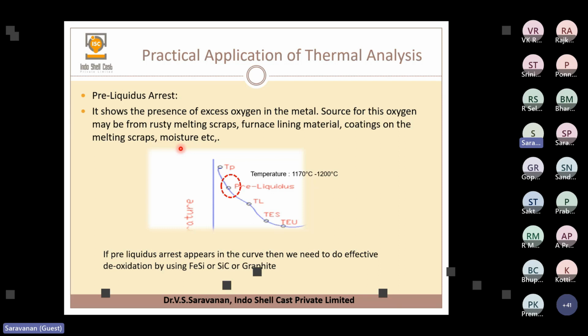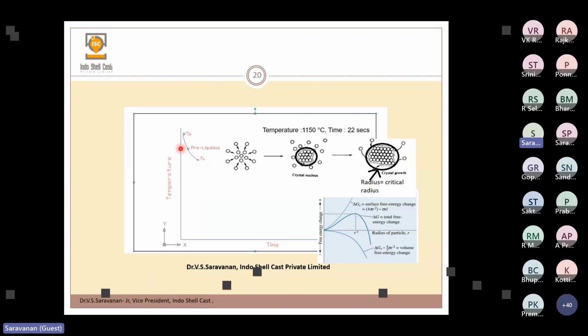If there is excess oxygen, maybe 100 ppm or something like that, then it will create issues. It will take more magnesium during magnesium treatment, so magnesium oxide inclusions will come and magnesium pickup will not be there. Maybe the nodularity percentage will come down. Sometimes there are gas defects, micro gas porosities inside the metal. So these things will be there, so we have to carefully control this pre-liquidus arrest, and take care of the scrap and all those things. And then again the temperature is coming down, then one more arrest point will come.